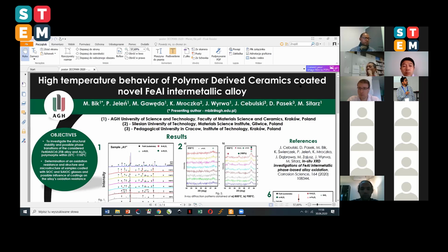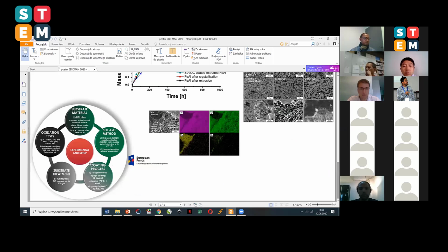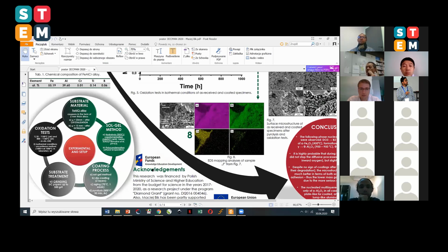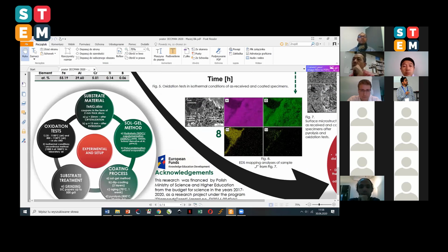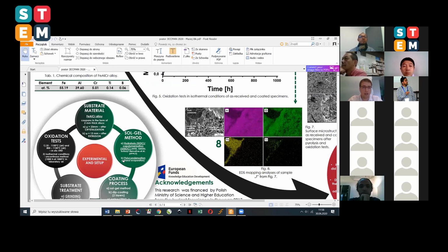So I would like to present the experimental part right now. So let me give just a minute. Okay, so here it is on the left. The alloy consists of around 40 atomic percent of aluminum, 5% of chromium, and some small additions of titanium and boron. So this is FeAl, the B2 phase, and the chromium, titanium, and boron are added in order to increase the mechanical properties of the material itself.